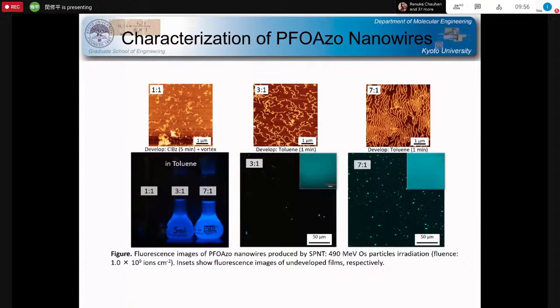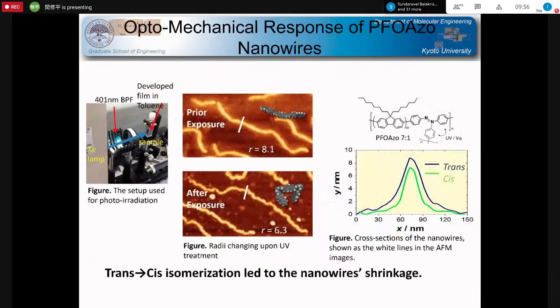And the fluorescence microscope has a very low resolution compared to atomic force microscopy. But anyway, once the nanowires can emit light, we can check the location of the nanowires simply by the optical microscope system. And the question is the morphological change of the one-dimensional nanowires against light excitation, and a precise trace of the morphology is also checked by the atomic force microscope.